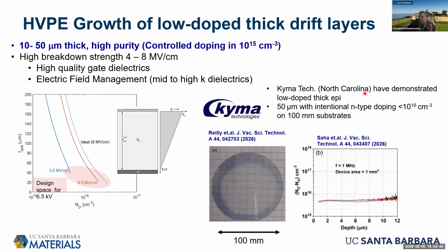Okay, and again, why am I emphasizing this low doping regime? Because that's what you need to get to high voltage devices. So to get to something like 6.5 kV, we need thicknesses in the range of tens of microns of material with low doping. And so getting this combination is tricky.